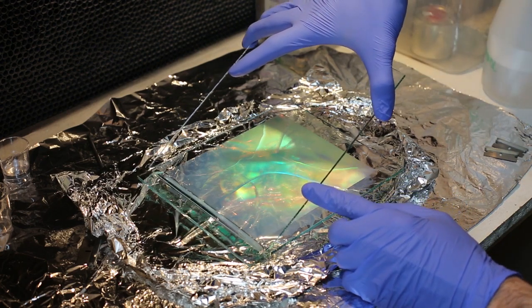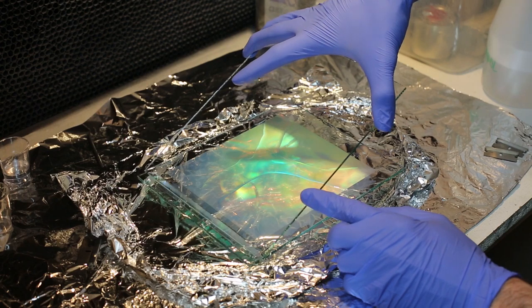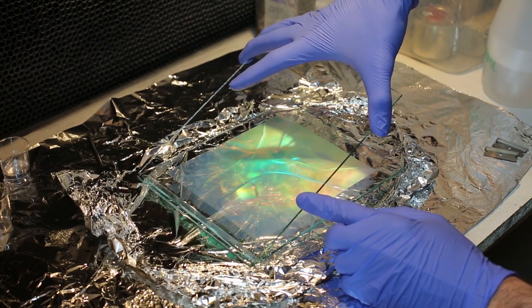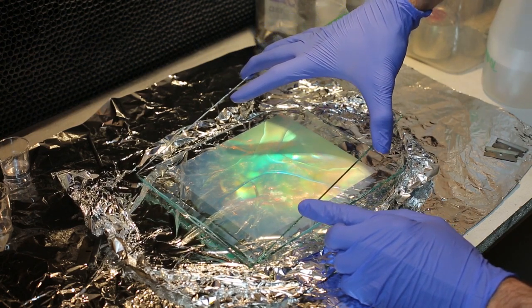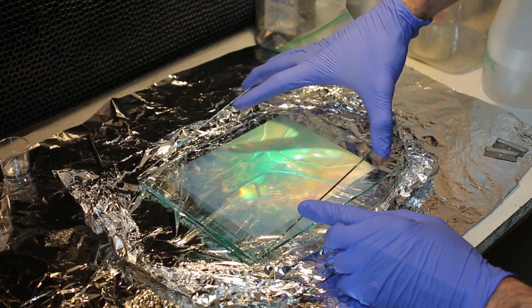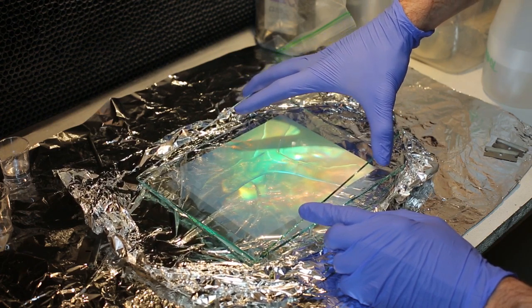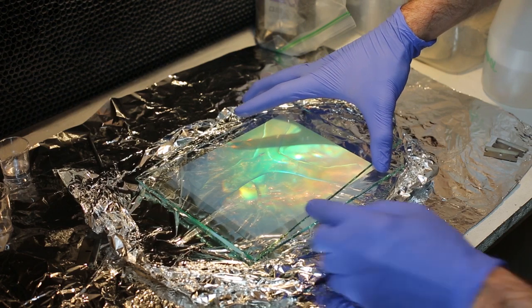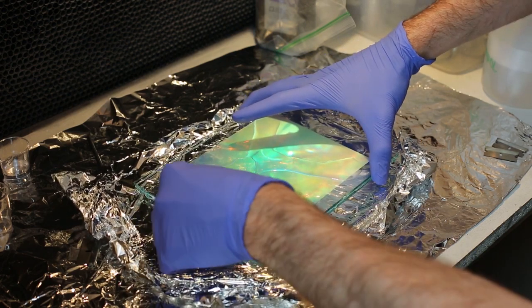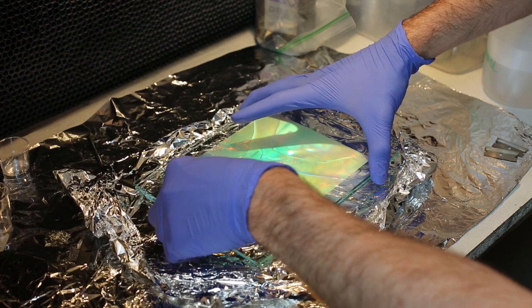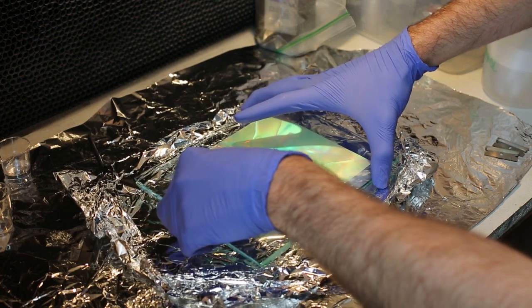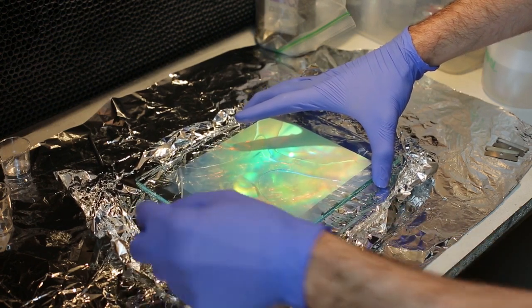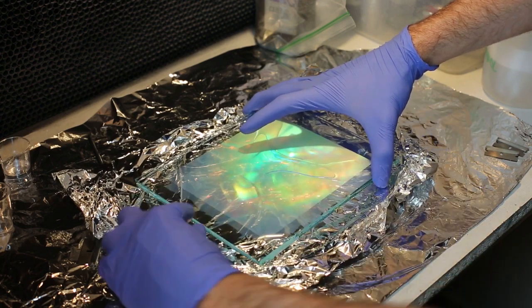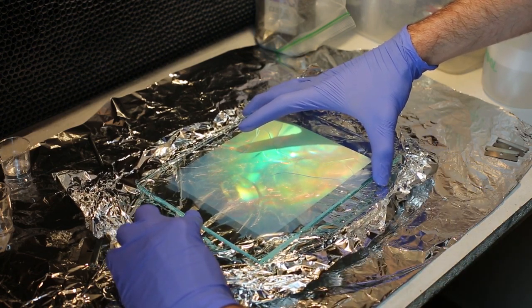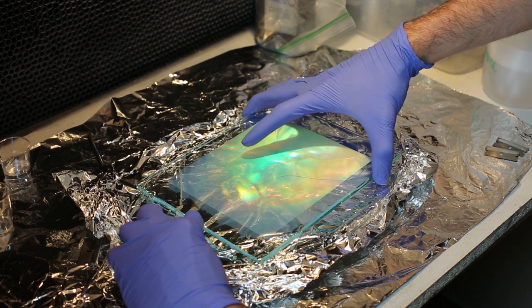I lower the plate very slowly and then rock the glass around a little so the glue disperses all over. Very slowly, I tilt the top cover plate and lower it towards the bottom hologram plate. You really want to do this in the slowest way possible, because if you do it too fast, there is a high chance of creating new bubbles. If everything works perfectly, the glue should move from inside out, covering the entire plate.